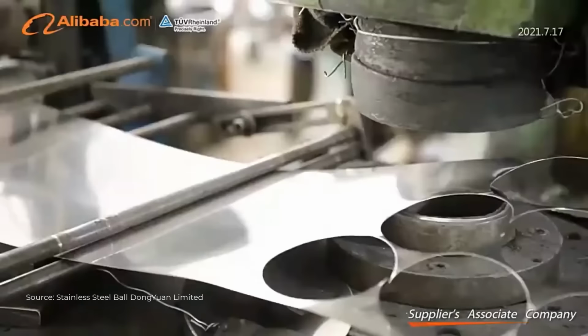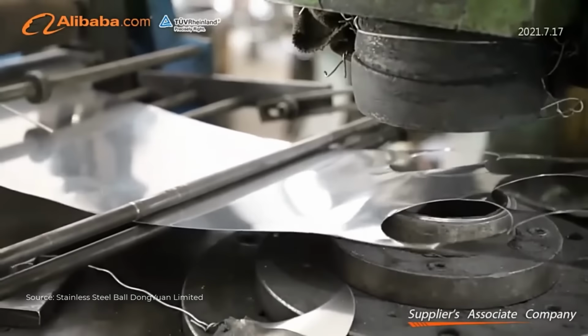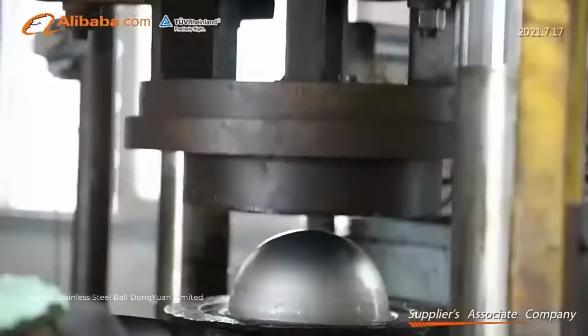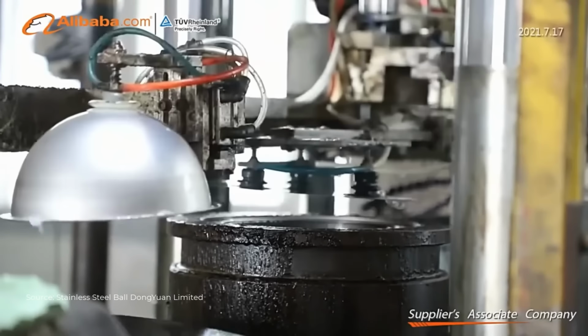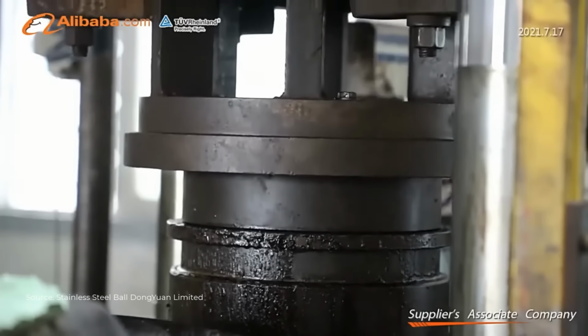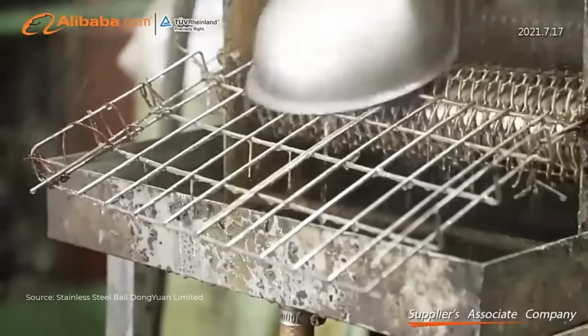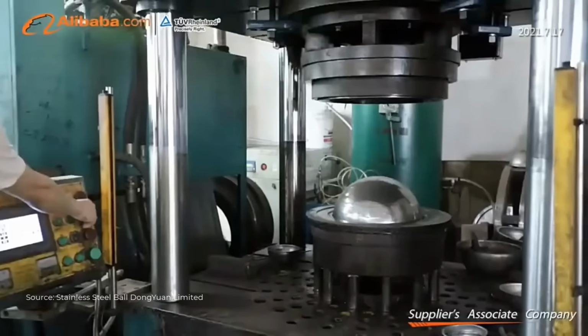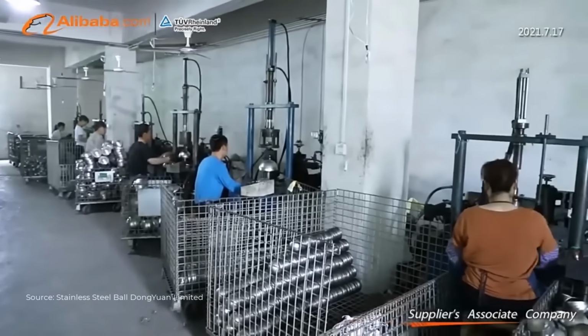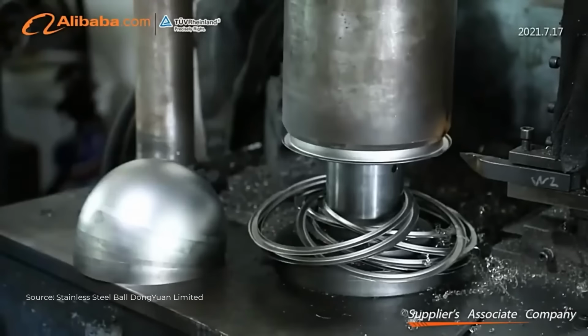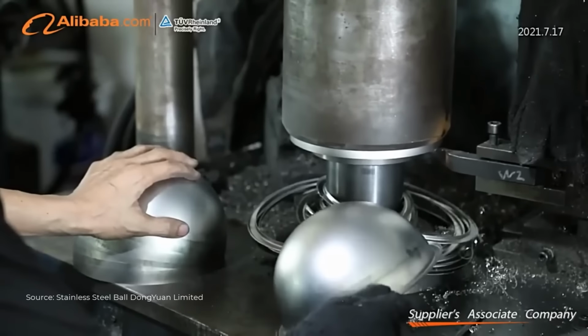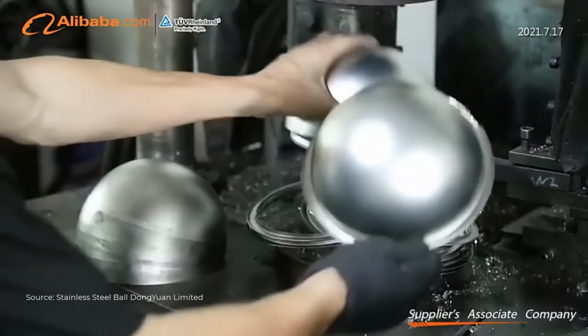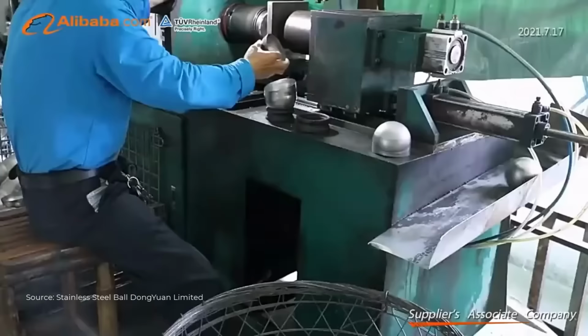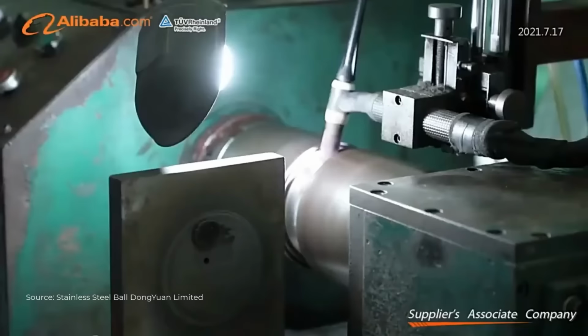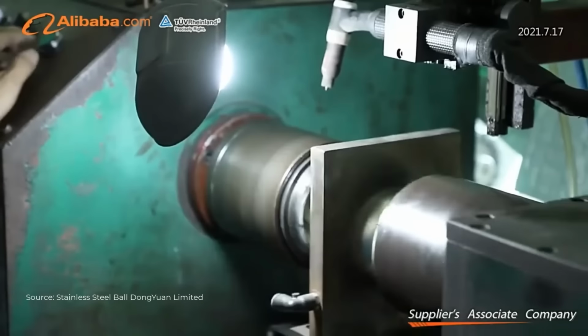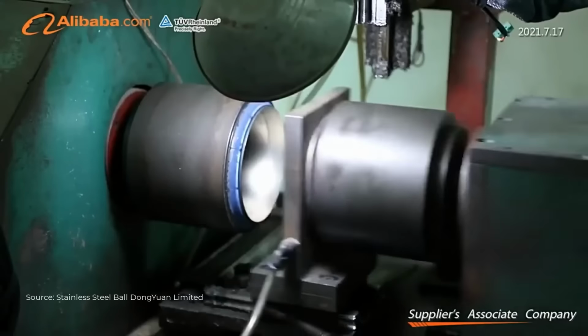The production of stainless steel spheres begins with selecting high-quality stainless steel sheets. These sheets are cut into precise circular blanks, which are then pressed into hemispheres using hydraulic molding machines. Two hemispheres are welded together by advanced automatic welding equipment to form a perfect sphere. After welding, the seams are carefully ground and smoothed to ensure a seamless appearance. The spheres then undergo semi-automatic polishing, where multiple polishing stages create a bright, mirror-like surface. Finally, each sphere is inspected for roundness, surface quality, and finish before packaging.